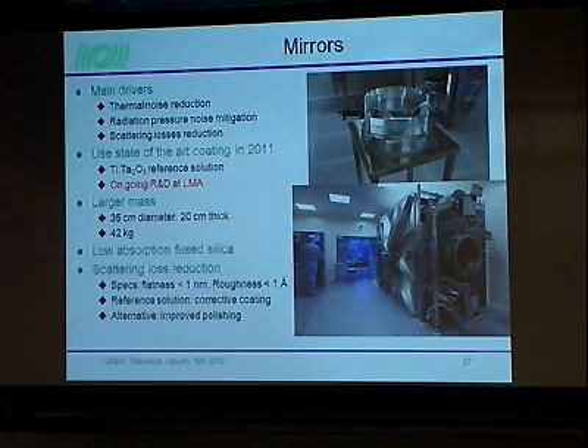And we will need to reduce the scattering losses. There is a quite strict requirement on the flatness of these mirrors that we hope to achieve by using corrective coating. Basically, you measure the surface of the mirror, you look where the mountains and the valleys at the nanometer scale are, and you put silica at the right place in order to improve the overall flatness of the mirror. This is the reference solution that we are planning to use for Advanced Virgo.